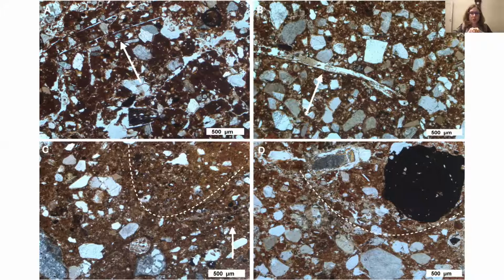Chaff voids are also mainly visible in the pre- and protopalatial samples, whereas seagrasses are visible starting from the protopalatial sample, but there is a huge increment in the neopalatial samples. Second, it was possible to identify microfissures caused by the progressive evapotranspiration of water-laden sediments, as the seagrasses inside the bricks cause long-term water retention. Third, you can see in the dotted line here, we identified some rotating features that could be associated with manufacturing practices such as kneading and pugging.